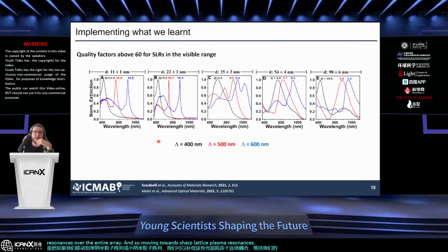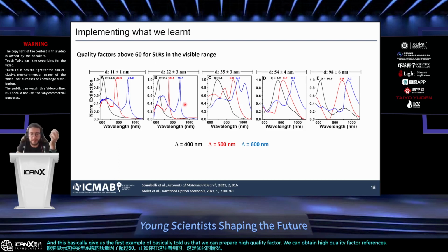So basically, by optimizing and implementing what we learned, we were able to show quality factors over 60 for this type of system. As you can see here, this is the most optimized case. And this basically gives us the first example showing that we can obtain high quality factor resonances using colloidal systems.